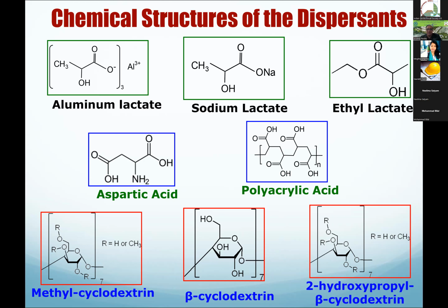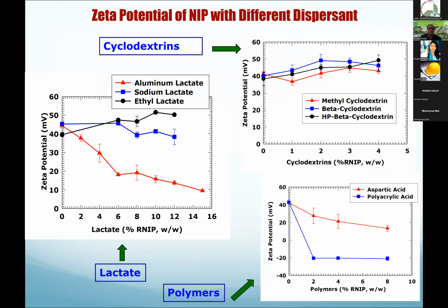So the whole idea of our research now would be, which of these are good dispersants for nano iron particles, and what should be their concentrations? So we do this test. We are adding lactate as a percentage of the nano iron particles. So whatever nano iron particles you have, the percentage of that. If I increase the percentage of lactate, of different types, aluminum lactate, sodium lactate, ethyl lactate, you see that one, right? So just increasing the lactate content.